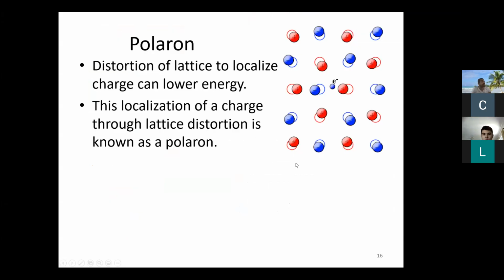Still works. Okay. Yeah, so if I'm to hold this charge right here in a lattice, you can see that these empty circles are the original positions of the lattice. You could think of a metal oxide where you have positive cations of the metals and negative ions of the oxygen, right? And so the oxygens get pushed away from this electron, and the metals kind of come closer. And what does that do to the potential of the lattice? You actually create a well that the electron now prefers to be in because it's more positive there. So this is called the self-trapping charge carrier. And this self-trapping with the charge is known as a polaron.